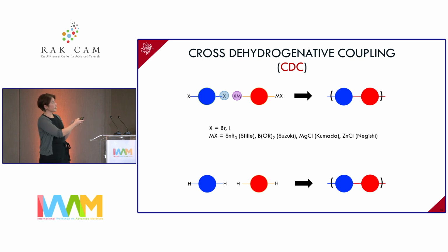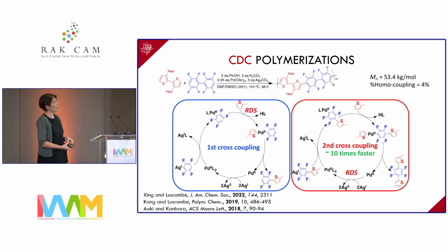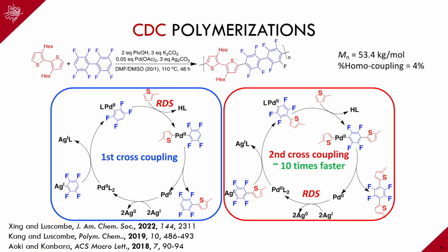Previously, I mentioned that the selectivity was governed by the fact that you had these functional groups that kind of controlled the coupling. But here, when you don't have any functional groups, how do you still make sure that you end up with an alternating copolymer? And so we've been able to do a lot of work in this area as well. I won't bore you with the synthetic details, but just suffice to say that we've been able to develop these reactions where you can start with these unfunctionalized monomers and be able to make high molecular weight, low defect semiconducting